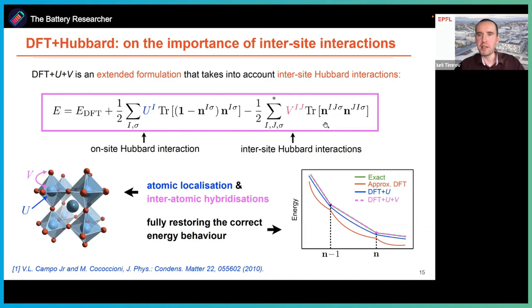So if the first corrective term wants to localize electrons, the second term does the opposite. It wants to delocalize them in order to restore the hybridization. So if we think of some materials with strong covalent interactions, we really need to use this generalized expression, because covalent interaction is physical and it should be there. Instead, if we use just the Hubbard-U correction, we will kill the physical effect and the result will be inaccurate. So this is state-of-the-art DFT plus U plus V.